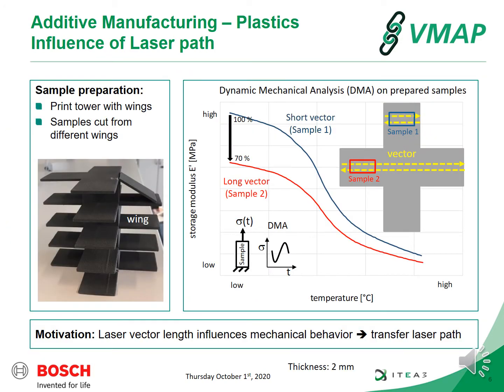Why is the laser path so important for 3D printed parts? You can see here how samples extracted from a print tower at different positions result in strongly different mechanical behavior. Sample 1, presenting a short vector length, behaves about 30% stiffer than sample 2, which had a longer vector length. The laser vector length is thus strongly affecting the mechanical behavior of the part and needs to be considered in the simulation of the printing process.